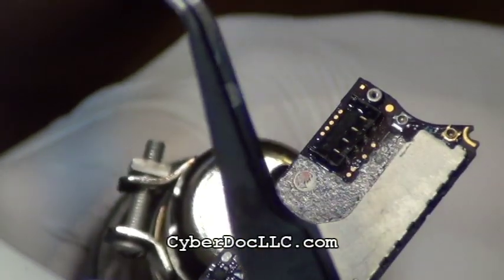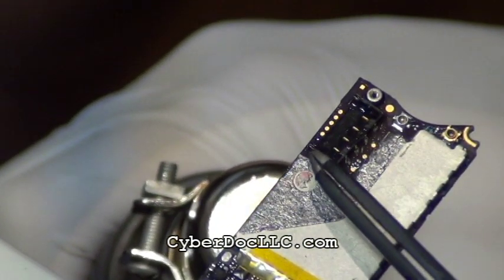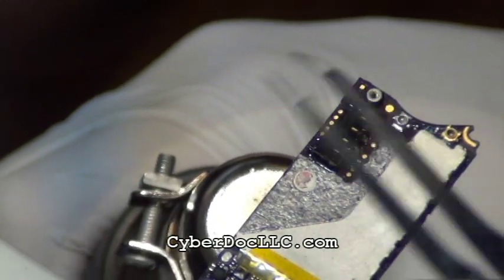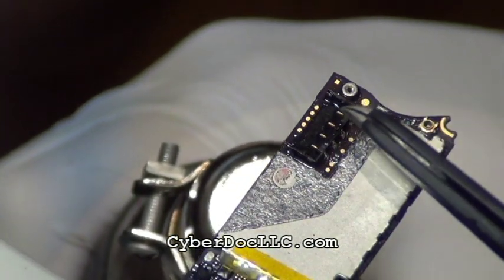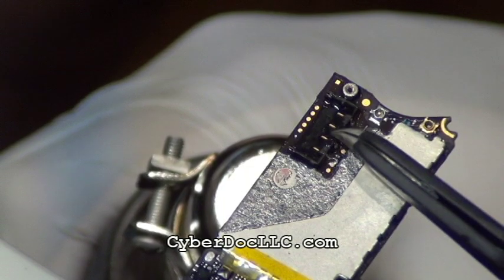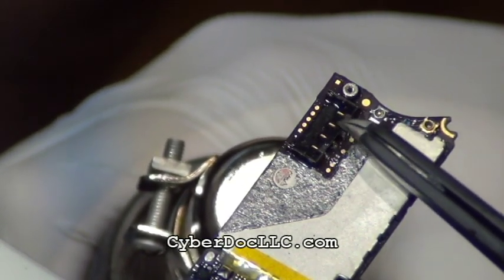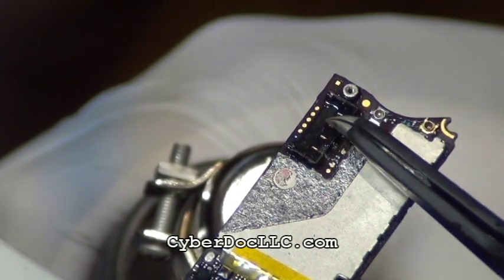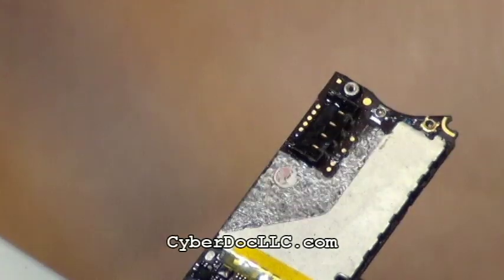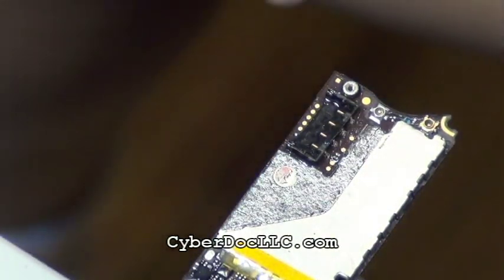And since I don't have a soldering oven, and I don't want to heat up the rest of the logic board other than this part, that's why I'm doing a local reflow. I use a localized hot air gun to heat it up. Okay, as you can see, this board right now is probably somewhere around 240 degrees Celsius, since the flux is not evaporating and the solder is being melted, so it's above 137 degrees Celsius. Once it's molten, like I did in the video, you want to poke at the connector a little bit, give it a little vibration and stress, so it can form a good bond with the solder pad and the connector.